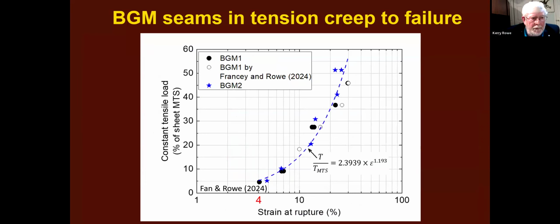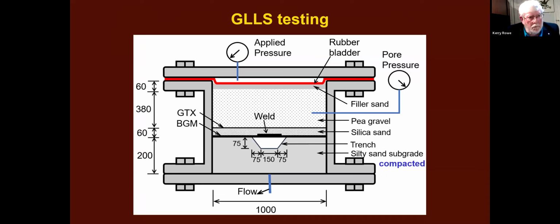Now, another way of looking at it is what is the relationship between strain at rupture and the stress that's applied? And you can see that if we only have 5% of the strength, we're still failing, but at a quite small 4% strain. The higher the load, the more it strains. And that's because the higher load gives you more creep. And eventually it fails in a brittle manner, but it is creeping for much of that time.